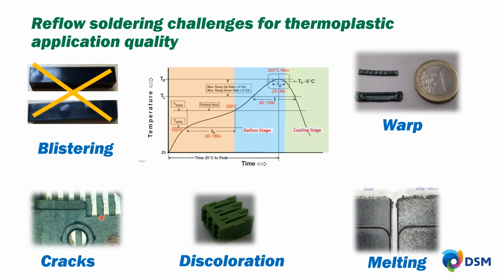You can see cracking, especially around insert molded conductors, where the material hasn't been able to resist the expansion and contraction of that heating and cooling process. Discoloration can become an issue for the connectors as they go through the heat. And warp, where the material yields to any loads or stresses either internally or put on it by the assembly process. The material needs to resist that warp and deformation under that heat, and flat out melting, of course. You have to have a material that has a melting point well above that which it sees in the reflow process.